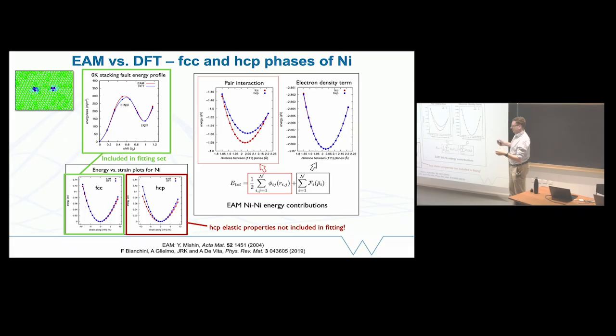So the electrons are actually doing very similar things in the FCC phase and the HCP phase. So the electron density contribution, which is one thing that goes into the model, is pretty much the same. The pairs need to do different things, and you can't fit a single simple pair function to represent these two different things. Once you've diagnosed that, once you've understood why your simulation is giving the wrong answer, you could go back and fix it, but it's hard to do that beforehand. You really need to dig in and do a post-mortem analysis of what's going wrong in this case.